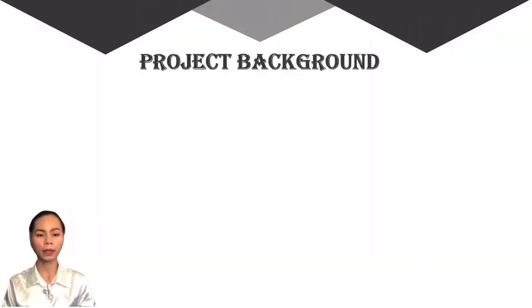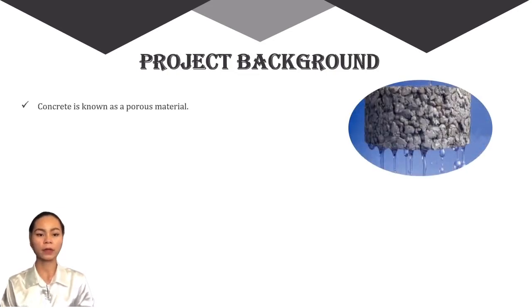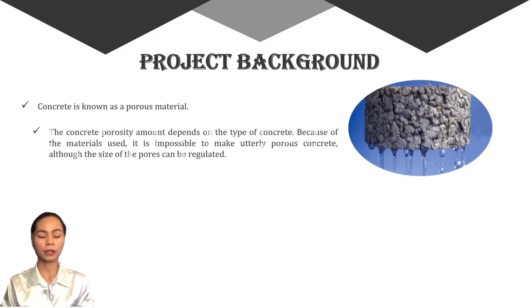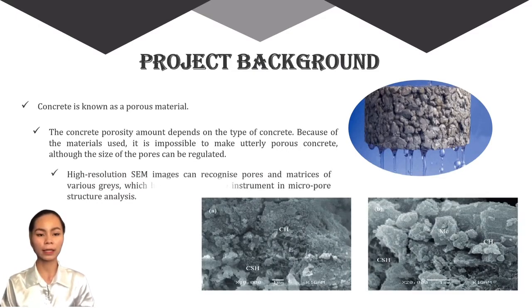As for project background, firstly, I want to describe a bit about concrete. Concrete is known as a porous material. The concrete porosity amount depends on the type of concrete. Because of the material used, such as aggregate, it is impossible to make utterly non-porous concrete, since aggregate has its own porosity. However, we can easily recognize pores and matrices of various grades of material with high resolution SEM images, which make it an effective instrument in micro pore structure analysis.